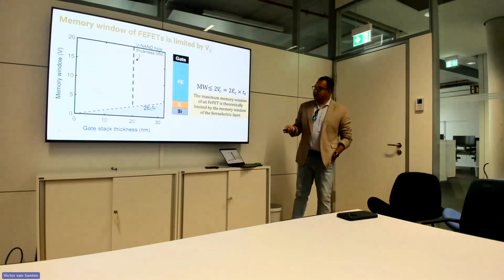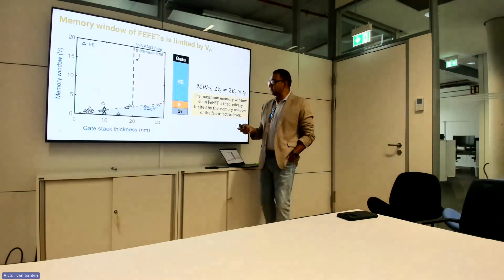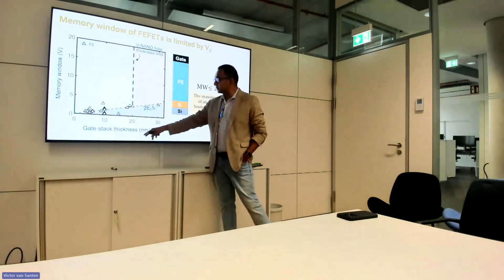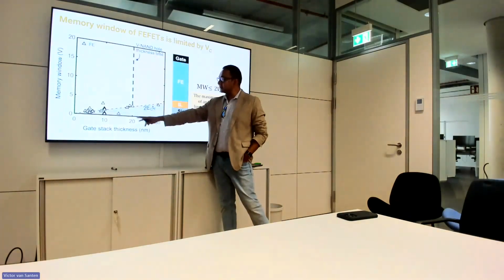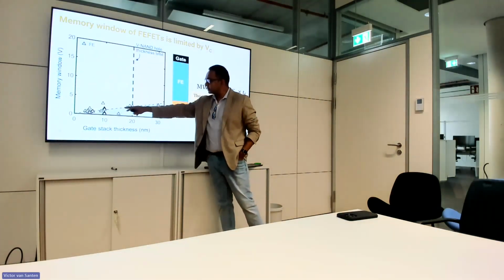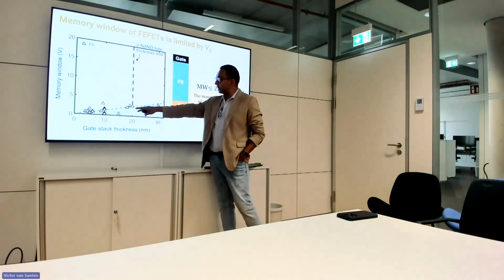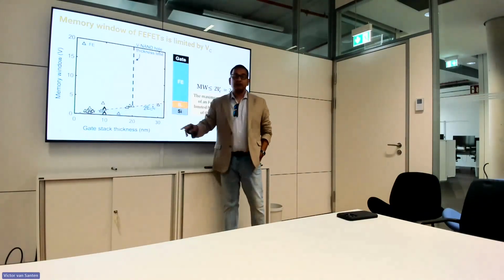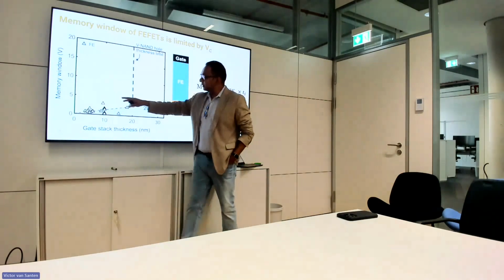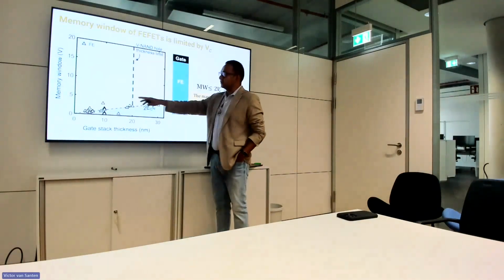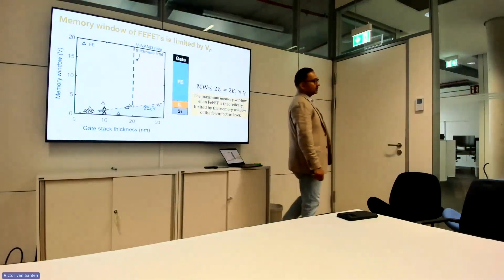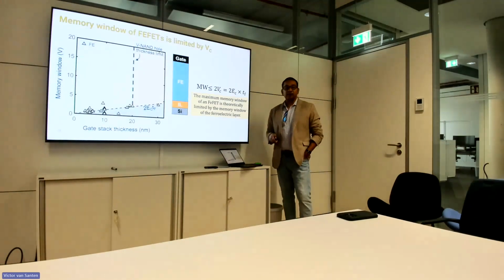So just plotting the same curves over here, same thing. If we looked at the literature back in 2023, gate stack thickness on the x-axis, memory window on the y-axis, you can see that most of the data points actually lie on this line over here. Where do you want to get to? We want to get to somewhere here, but if you use a pure ferroelectric, you cannot actually get to that 6.4 volt memory window line.